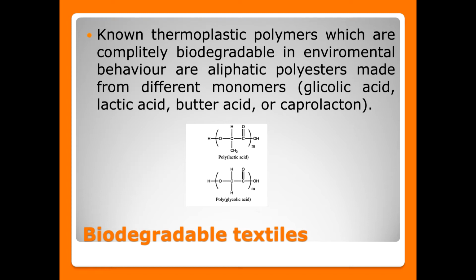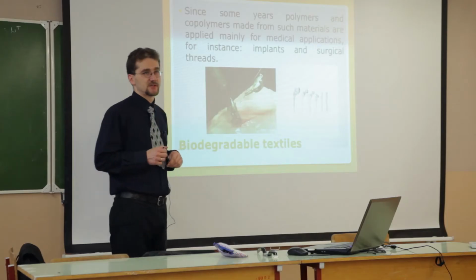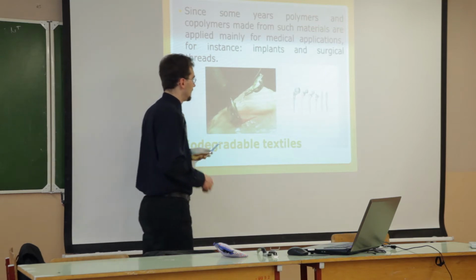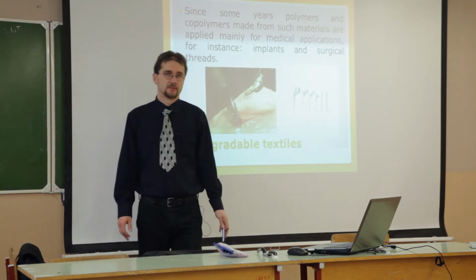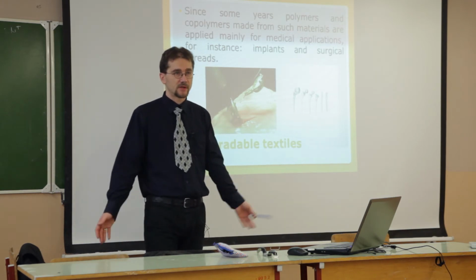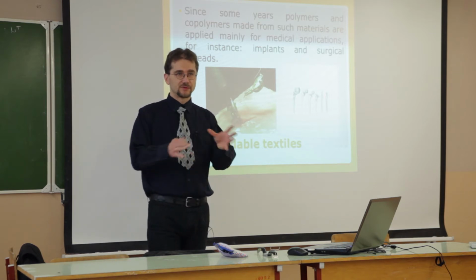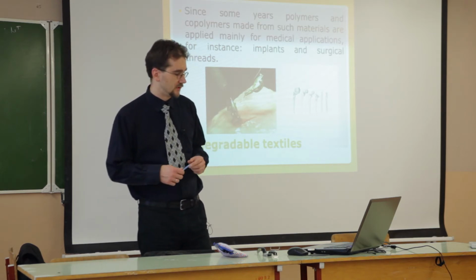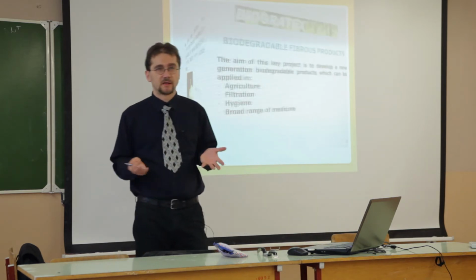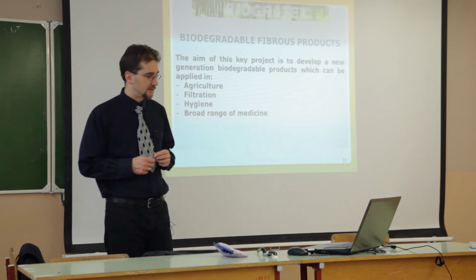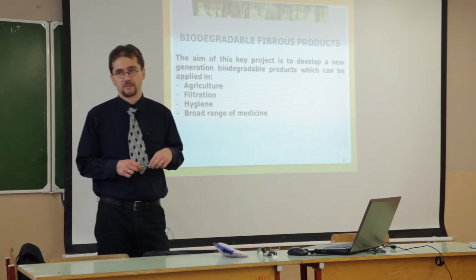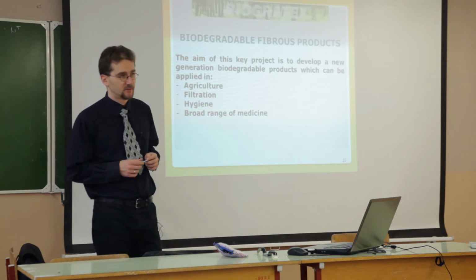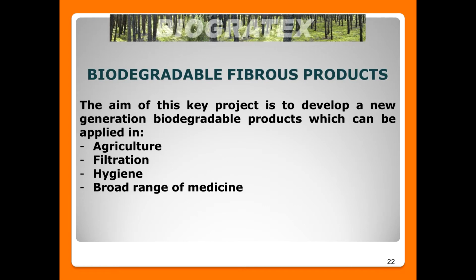The advantage of using polylactide is that the time of biodegradation is different in different conditions, and we can estimate the time. For example, we can produce polylactide which will be biodegradable in 6 months. That is enough for our organism to build different structure close to this material, and it will be degraded to lactic acid. Lactic acid is produced by our body, and it is very good for the implantation process. Why am I talking about polylactide?